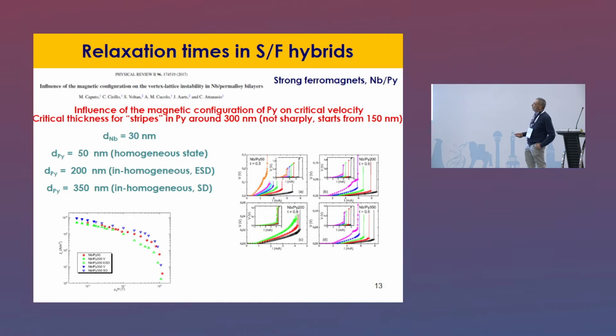So one whose thickness was similar to the previous one, 50 nanometers, in which the magnetization is always in plane, and the other 2, which I will not go into details about here, but in these 2 cases the magnetization has a component out of the plane, going up and down. So stripes develop in the system, and we measured the IV curves in the 3 cases.